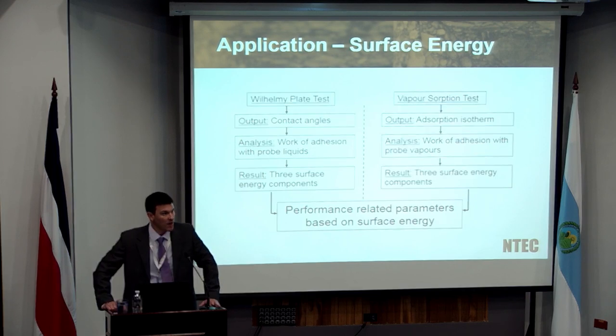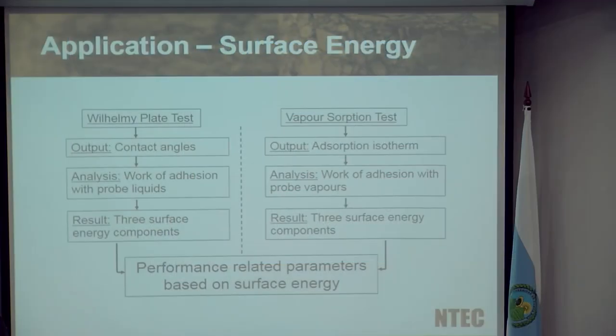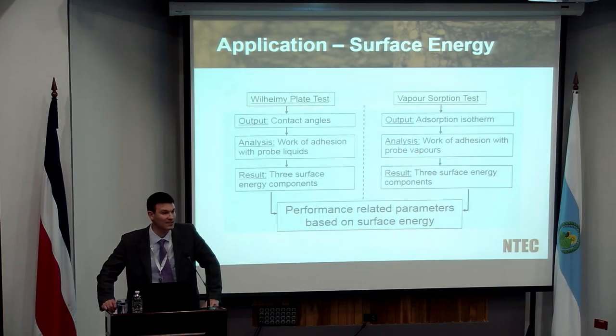So just quickly, so far what we've looked at is an approach where we said, let's look at the fundamental behavior or the fundamental parameters that are controlling adhesion that effectively will resist in some form or the other the effect of moisture damage or stripping. And we've looked at two different approaches. We've looked at the bitumen by using a Wilhelmy plate, measuring contact angles, and we've looked at the aggregate in terms of looking at vapor absorption. But those individual values on their own don't really tell us a lot. We now need to come up with a way of combining them.